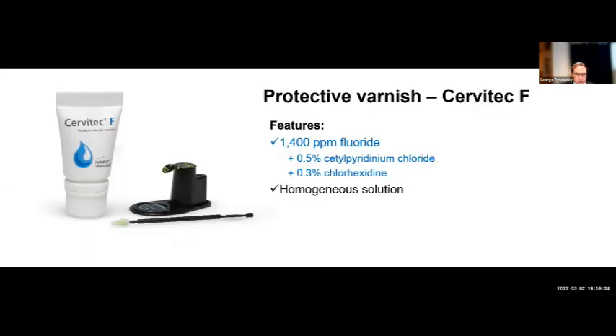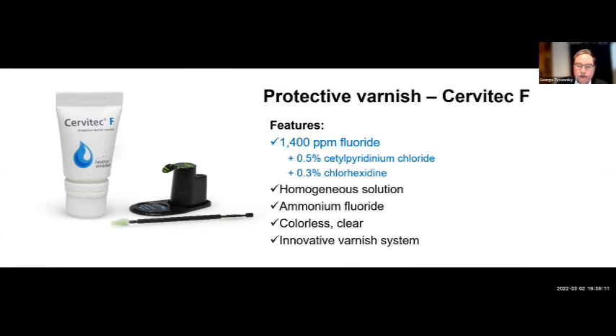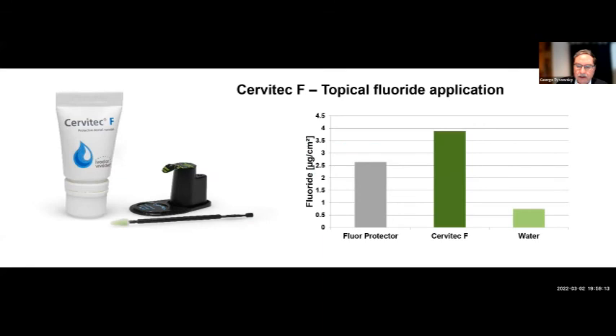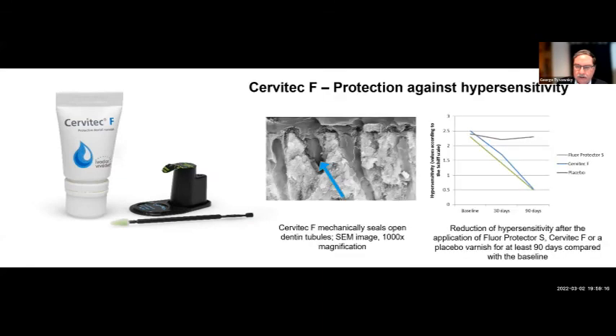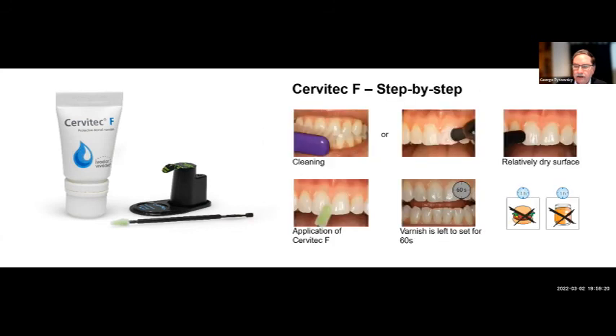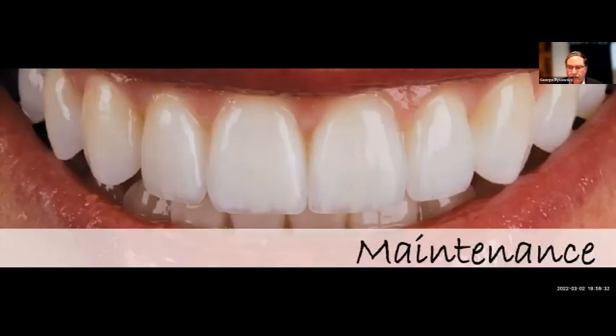And the other varnish we have is a combination chlorhexidine and fluoride material called Cervitec F, and it provides a good fluoride benefit relative to the application. It seals the tubules, also as a desensitizer. And then again, the sequence here is you clean it, you prophy it, dry the teeth, apply the Cervitec F, let the varnish set for the appropriate time, and then let the material provide a benefit. So maintenance of restorations is a very critical factor as well.